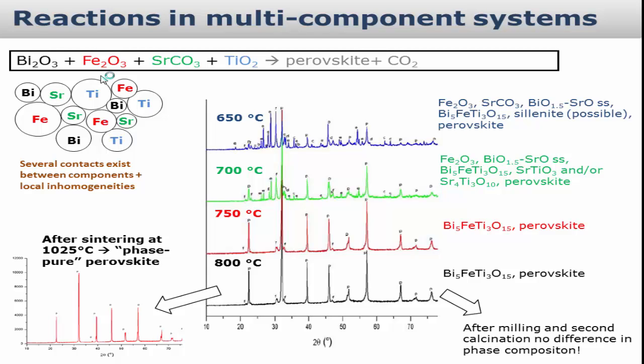So what you usually do is press the powder and go to high temperatures to sinter it, and you hope that these secondary phases will then react once you go to higher temperatures. And this is exactly what happens, apparently, when you look at the X-ray diffraction pattern. After sintering at 1025 degrees Celsius, you see that it's phase pure. So you're happy, and here you can take a sample, put electrodes on, and start to measure, which is the most exciting part.